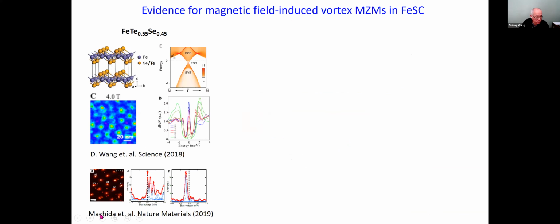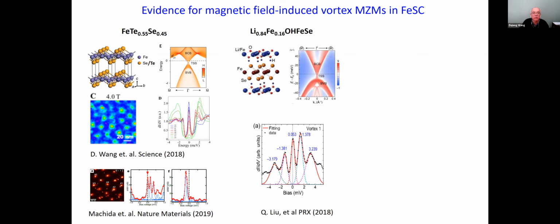And later on, Hanaguri's group has this ultra high resolution measurements that makes it even more convincing. Of course, there are both vortices with and vortices without the zero energy mode. You can think of this as having both abelian and non-abelian vortices coexisting because of the inhomogeneity of the surface. Now, this is quite universal. I want to make the point that this is not just in FTS. This is FeSe. FeSe by itself doesn't have surface state, but if you interpolate this way, you get topological surface state. And then in the vortex, you see the zero energy bound state.